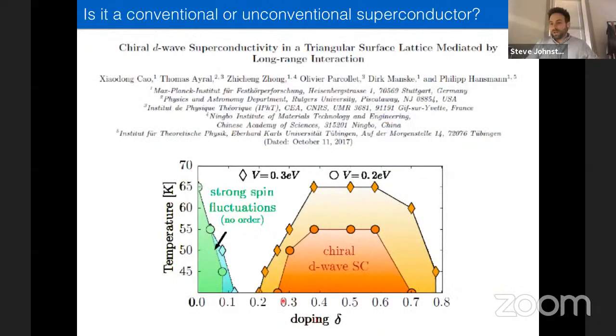So then the next thing we wanted to look at was the unconventional mechanisms. Andrei Chubukov some time ago predicted that these triangular lattice systems should have chiral d+id superconductors. There's also follow-up work done by Philip Hansmann's group, where they actually calculated a phase diagram, and they predicted that the chiral d-wave should have a superconducting dome as a function of doping in a triangular lattice Hubbard model. And so the next natural question was, can we start looking for these sorts of order parameters in the system?